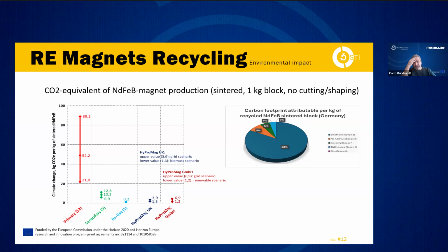If you look at the CO2 equivalent, this was done by Enzo Granello, who is also in the call. He compared the LCAs and the TEAs that we made in the projects with short loop recycling with literature, which means with LCAs of primary material and of secondary material. And what you see here is a range, and the range is surprisingly large for primary material, between 21 and 89 kilograms CO2 equivalent per 1 kilogram of block of magnet.